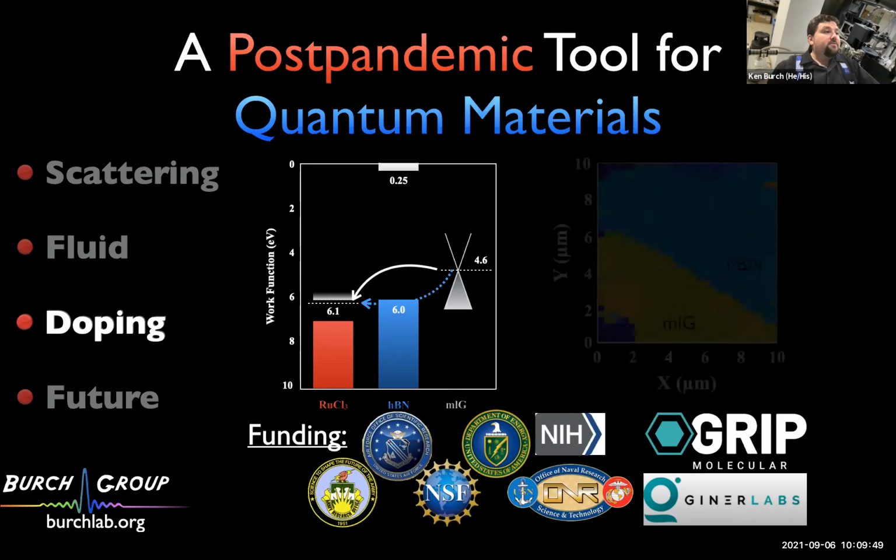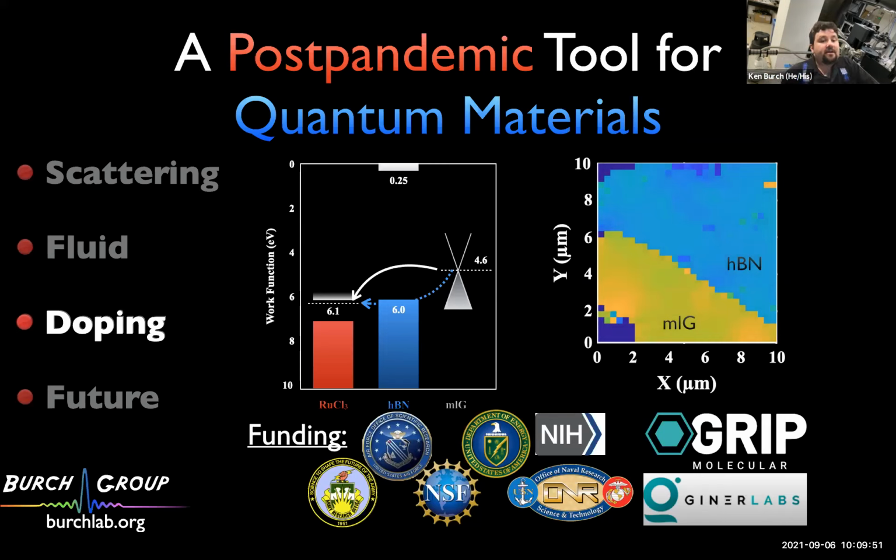What's more remarkable is the valence band of hBN basically lines up with the conduction band of ruthenium chloride, so that you can still get a charge transfer even with hBN in the middle. I will show you the various things we've done to optimize this effect and also to measure it using Raman scattering. Here I'm showing, roughly speaking, the extracted charge when we have ruthenium chloride sitting either directly on monolayer graphene or with a BN layer between the monolayer graphene and the ruthenium chloride.